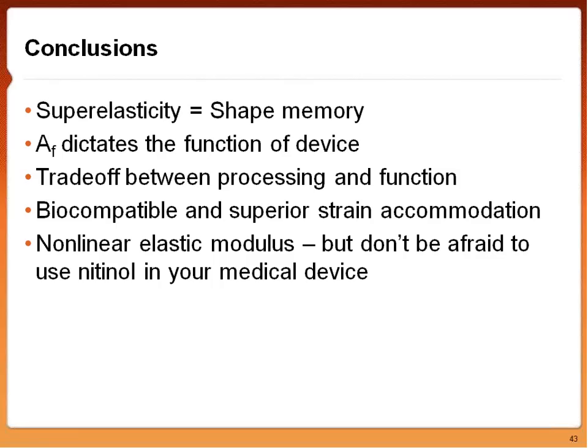You have a trade-off between processing and function. If you want a slightly stiffer device, you're going to have to pick a correct processing time that's not going to hurt your upper plateau stress or your ultimate tensile strength. Nitinol can be very biocompatible, and it's the best material on the planet, in a sense, to accommodate strain-based applications. And finally, even though it has a non-linear elastic modulus, don't be afraid to use Nitinol in your medical devices.